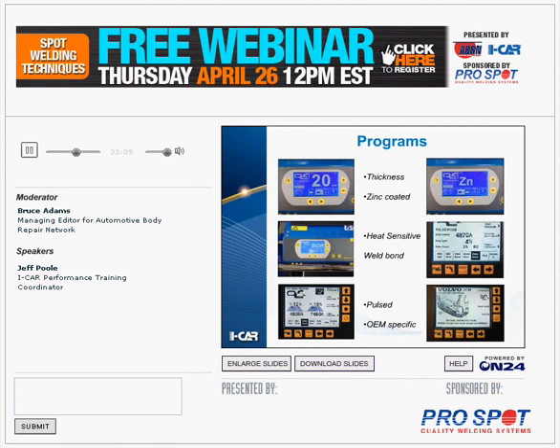Next thing we might have is the steel thickness as we look at a few more parameters here. Most of the equipment I'm familiar with typically has you measure one of the panels. We may have situations where the thickness is based on the combined thickness of all the panels, so it's going to be really critical that we know our equipment very, very well. But this is typically a starter setting for that particular machine, and then we can tune it up or down slightly as necessary. It's typically given in millimeters.